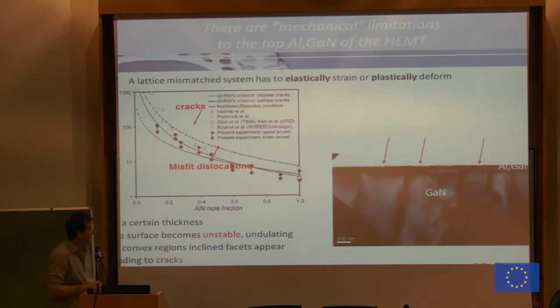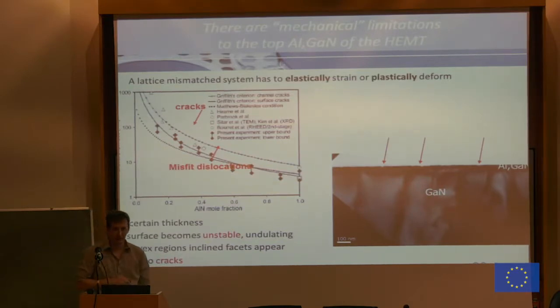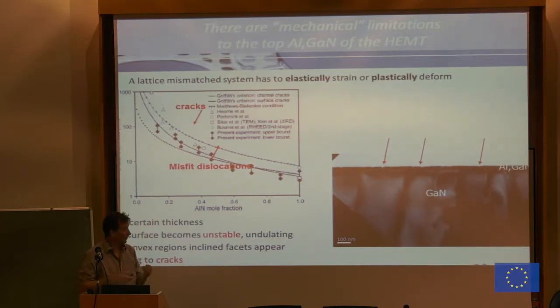But the example I really wanted to go into was this one here. It's again the growth of aluminium gallium nitride on top of gallium nitride, because this, as was explained yesterday and in the beginning, is really the core structure of your HEMT device. It is what you need to do. You grow a thin layer of aluminium gallium nitride on gallium nitride, and if you want to maximize polarization, you preferentially want to have a lot of aluminium in this layer.